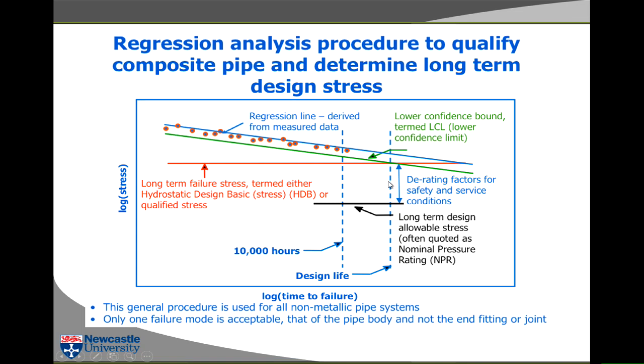Well, if you have a company and you're developing a plastic pipe product, you have to show that you know this relationship between time to failure. Remember, the dependent variable is on the horizontal axis this time, just to make it confusing. So it's like a fatigue curve. So the time to failure and how it is related to the hoop stress which is applied to the material.